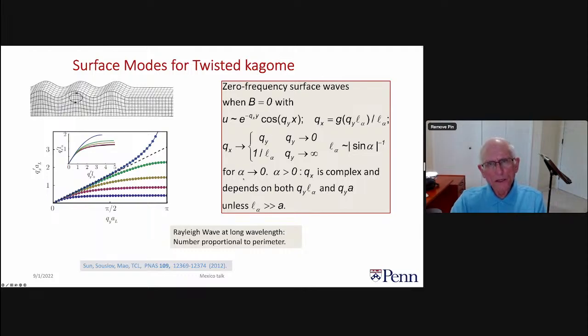And you can see that we get a length scale, which is the inverse of this QY. Well, this is the one that's wrong. I apologize for that. When QY goes to infinity, this goes to 1 over L. And when it goes to 0, it goes down to 0. So this curve is showing the penetration depth as a function of the amount of twist that we've done, the twisting angle alpha.